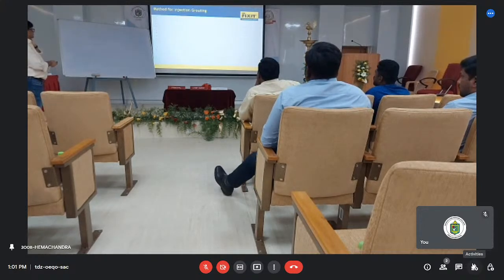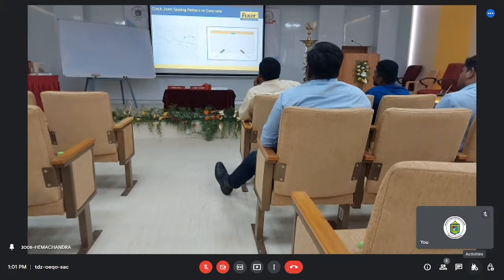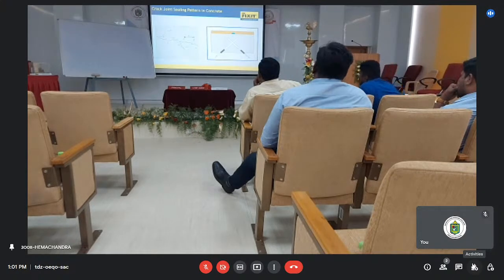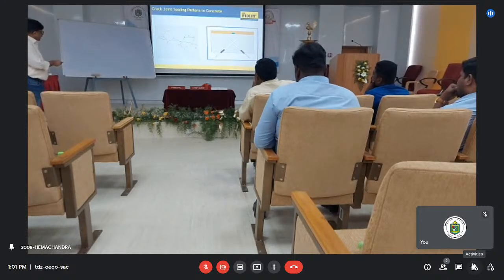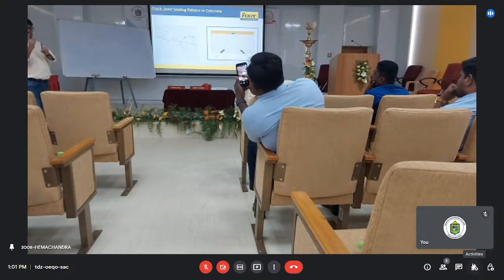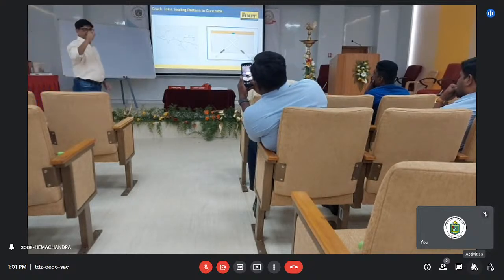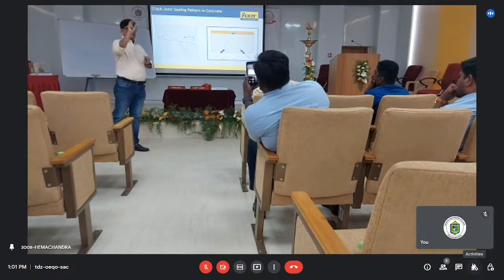I will first show you the pattern. You see this? This is the crack line. Your drilling of the holes should be on opposite sides, exactly like this. It should not be on the mouth of the crack. It should be on both sides of the crack.